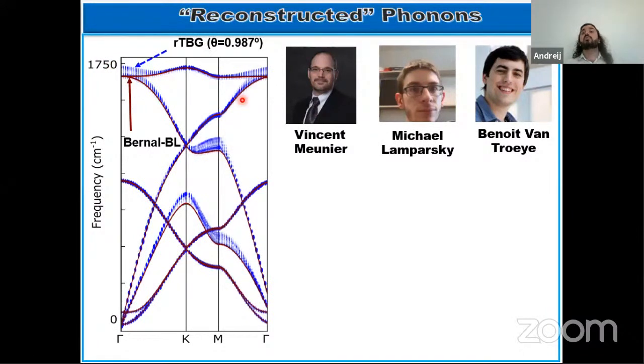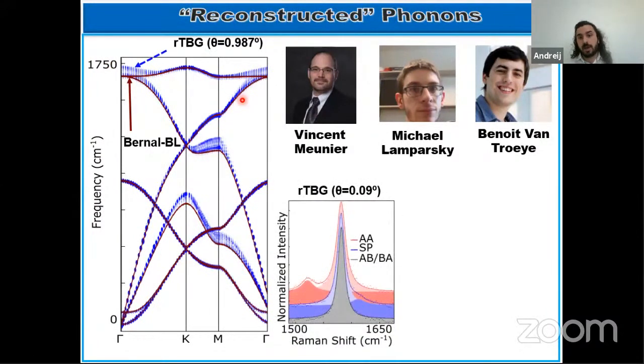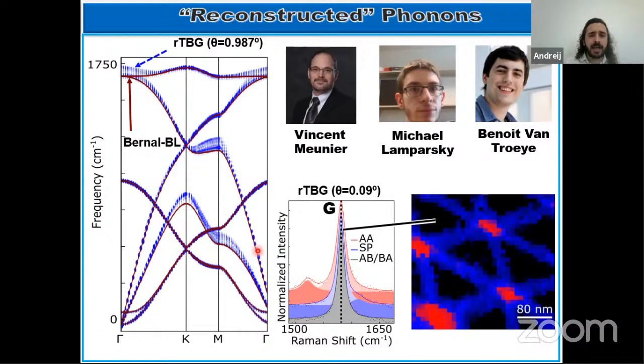And what do we see in our experiment? Remember that the nano-Raman gives spectroscopic information at the nanoscale. So here I show nanospectra at the AA site, the SP site in blue, and the AB/BA region in black. These peaks are close to the G phonon, okay? And at the AB/BA site, we only see the G band, only one peak.